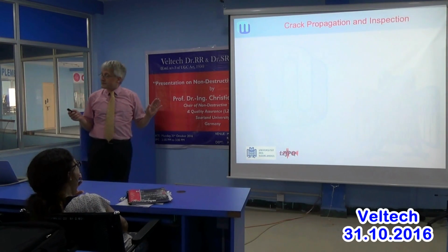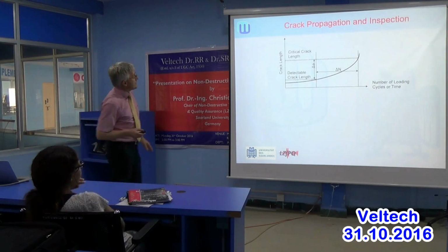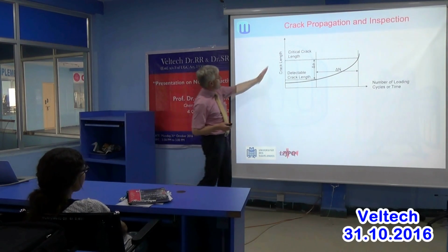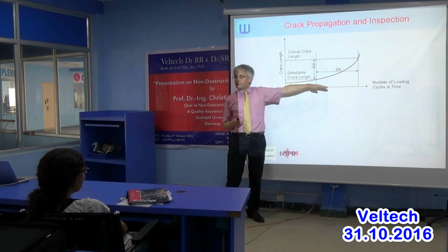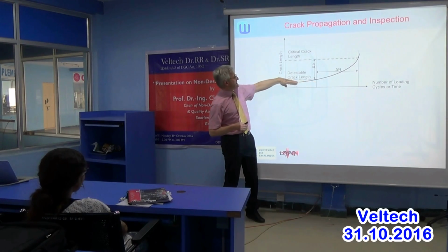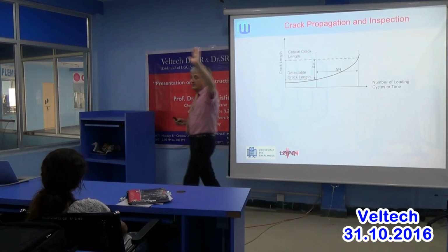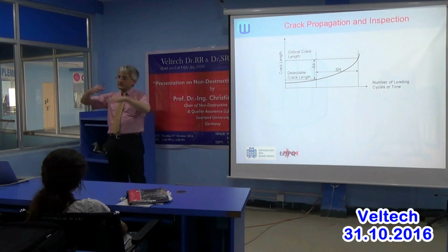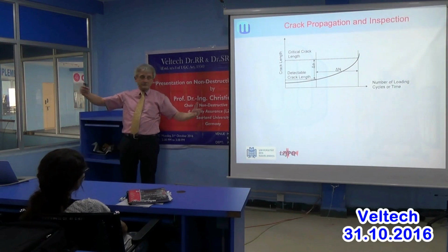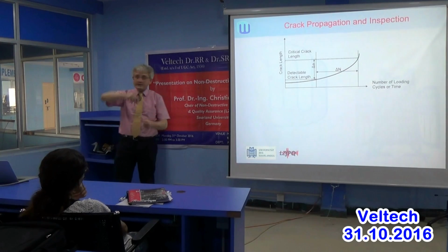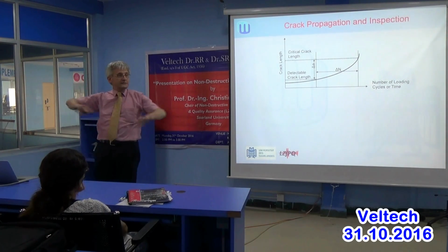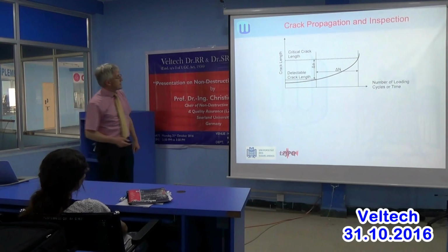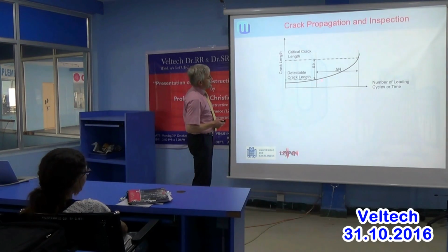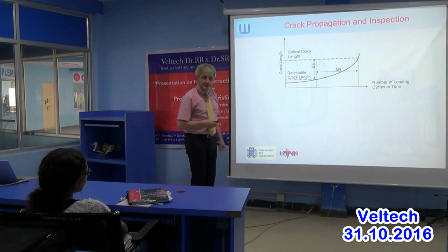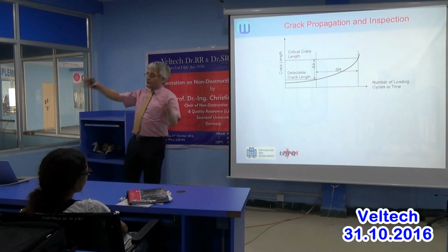Good, now we allow for damage, and damage is of course cracks, as we're seeing. So we can describe how a crack propagates over a number of cycles, and this is a sort of non-linear behavior. The longer the crack becomes at the same load, the quicker it propagates. You may also know that. If you pull on something and the crack is long, you have the same load and suddenly the crack propagates very quickly.